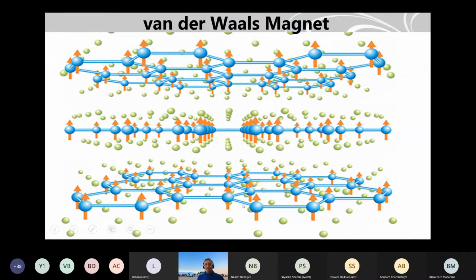Okay, then I go to another system, which is actually a van der Waals magnet. We wanted to induce magnetism in graphene by proximity. What you have seen is that graphene with MoS2 gives spin orbit proximity, and graphene with a magnet can also give magnetism, meaning proximity induced magnetism.